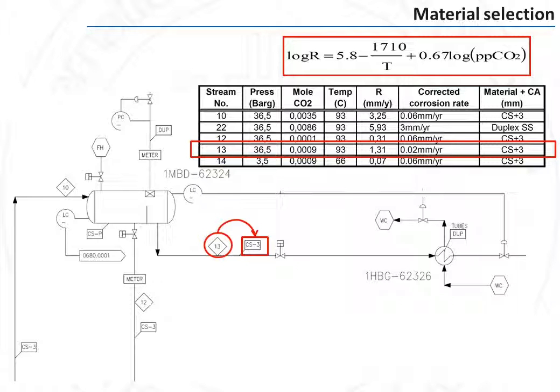If the result is a wall thickness loss over the facility's life of less than 6 mm, then ordinary carbon steel can be selected with a corrosion allowance up to 6 mm. If the overall wall thickness loss is more than 6 mm, a corrosion resistance alloy such as stainless steel must be selected. This calculation is done for each and every line of the facility and the material is selected accordingly.